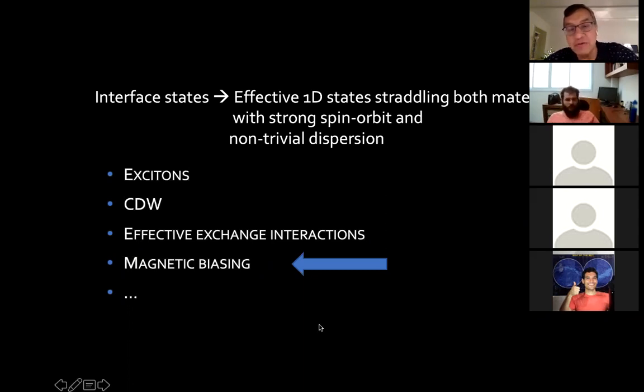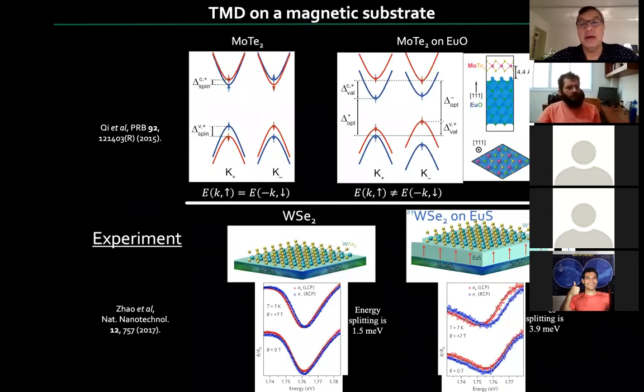You can imagine a different effect in that I have these robust states that live on the edge or the interface and ask what would happen if I magnetically bias them. In other words, put the ribbon on top of a magnetic system. And so here is what happens. This is a bit of an intro before I go to the ribbon. Remember I told you that there is this valley spin locking in the system so that the two valleys have opposite spins. And when I deposit the material on a magnetic substrate, there's an exchange bias, so-called. And what that means is that, say, the spin up gets shifted down in both cases, while the spin down will get shifted up, for example.